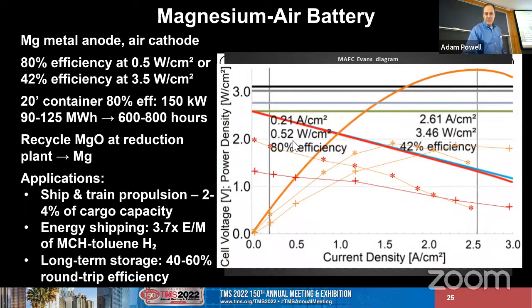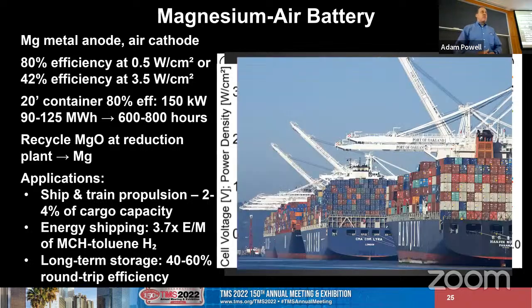Yeah, and here's what we achieved: 1.9 volts, which is close to the 2.3 theoretical. All right, maybe I'll just finish presenting this slide. If we can follow this model curve, then we can get to 80% efficiency. As it is, this is about 60% efficiency, and that would correspond to about 90 megawatt hours in a shipping container, compared with the best lithium-ion battery, which is 4. So 20 times more energy. So if you were recharging your ship by swapping in these containers, you could go 20 times farther per container with this battery, if it works.